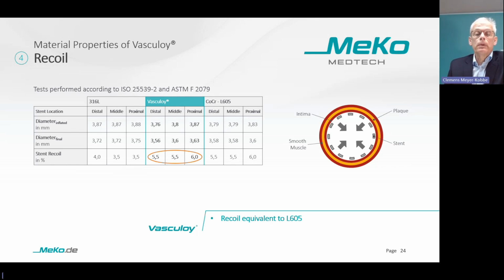To compare the three materials, 316L, L605, and Vasculoy in real-world circumstances, MeKo manufactured stents out of these three materials with identical design, so the same geometry, strut properties, etc. These identical stents, only different in material, were tested for recoil. The table shows the recoil. 316L has the lowest strength and therefore lowest yield strength. That means it starts to deform at lower forces. So it has the lowest recoil. Vasculoy and L605 have similar but slightly bigger recoil values.